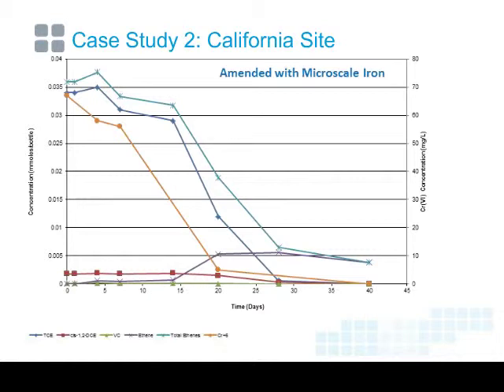We saw the chlorinated ethenes, the TCE drop out, and the cis-DCE drop out by about, between day 25 and day 30. We saw very little production of ethene, which is a typical result with ZVI. You often get acetylene being produced, so you're getting contaminant destruction all the way to acetylene, ultimately CO2, and so you lose all your mass, and that's a great result there.